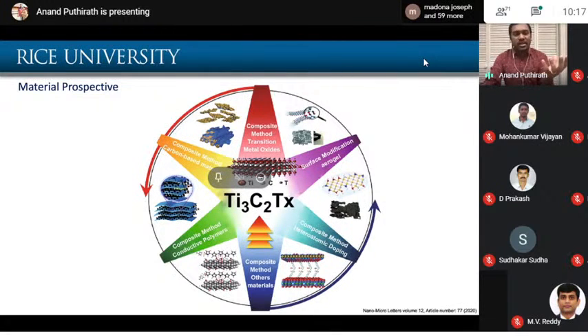So we want a moderately conductive material that can accumulate charges at individual points so that you can have a higher double layer, etc. That's why, if you look at the materials used for supercapacitors, activated carbon is not that conducting, but still has a good surface area. So sometimes you might want to add conductive additives to connect the non-conducting materials so that the charge can go to all the areas.